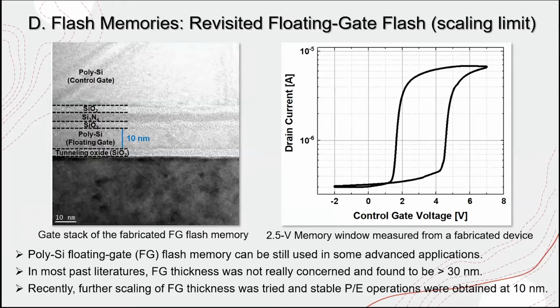And for flash memory, we revisited floating gate flash. Before about 2009 or 2010, as far as I remember, when charge-trap flash gained predominance in flash memory, floating gate flash was predominant. Floating gate means the gate is prepared from a polysilicon layer. In most of the literature, the thickness of the polysilicon floating gate was more than 30 nanometers, 40 nanometers, 50 nanometers or so.